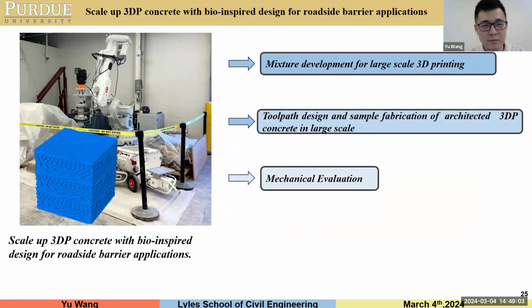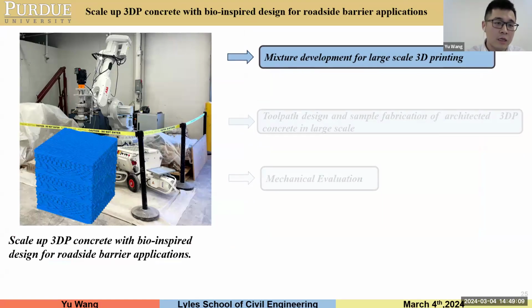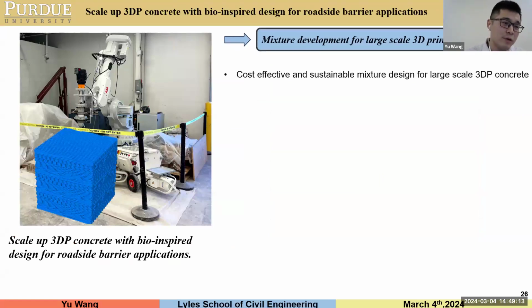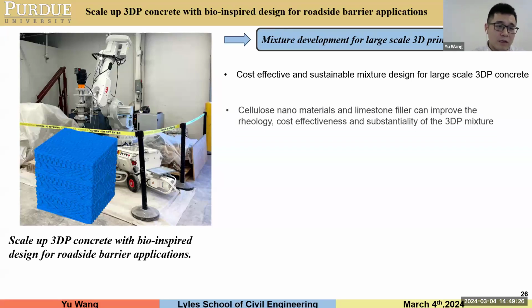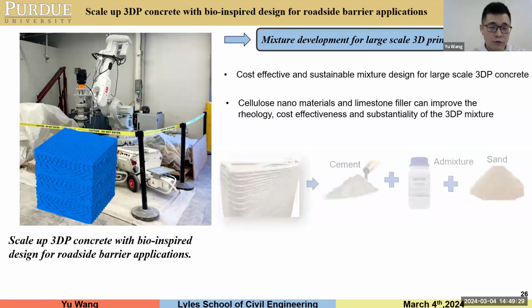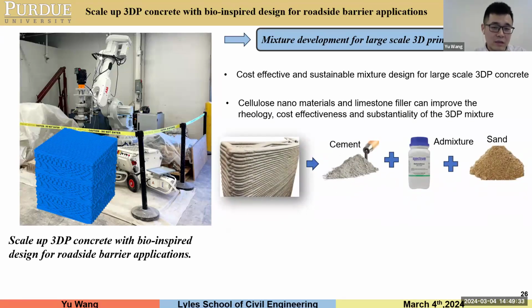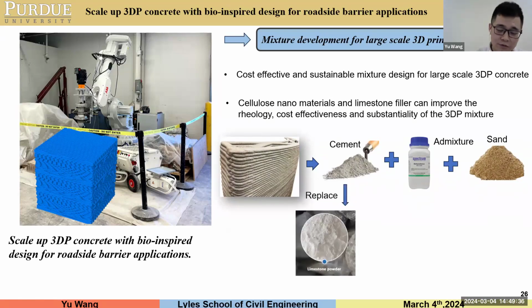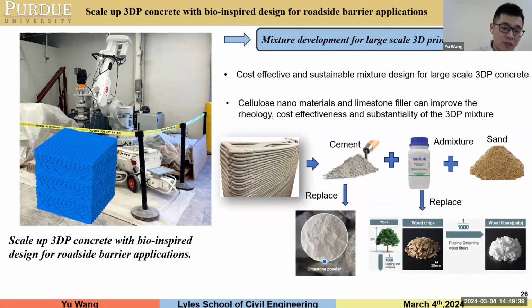We need to start with material development, then we need to study the toolpath design, and then we conduct the mechanical evaluation. We start with the material development, because for 3D printing concrete we also want our material to be more cost effective, since as I mentioned before, the current solutions suffer from high cost. So we also target making our 3D printing concrete cheaper. The expensive component is the admixtures, like the viscosity modifier admixtures. We are studying replacing this admixture with a cost-effective natural admixture, cellulose nanofiber, and we are also studying replacing the cement partially with limestone filler.